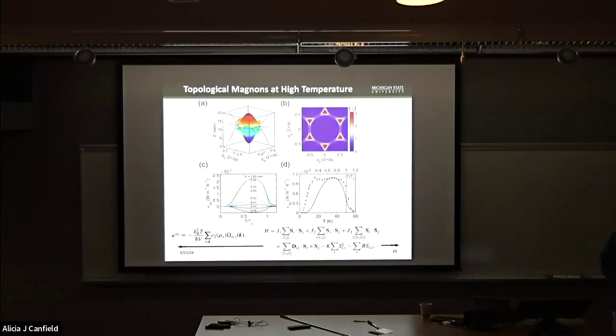To further understand the mechanism of the thermal signal that we observe here, we collaborated with a theorist who did the band structure calculation as well as the thermal conductivity calculations. The calculation was done based on a 2D Hamiltonian on the honeycomb lattice. This is the Hamiltonian, where we consider the first three neighboring interactions within the plane. The next terms are the DM interaction, the anisotropic interaction, and the Γ interaction.